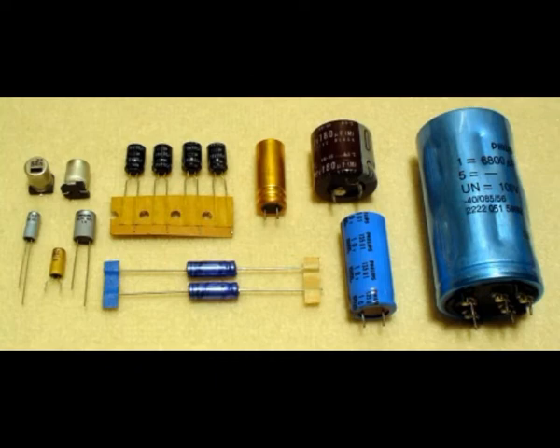This very slow drying out of the electrolyte depends on the series construction, ambient temperature, voltage and ripple current load. Lowering the electrolyte over time influences the capacitance, impedance and ESR of the capacitors. The capacitance decreases and impedance and ESR increase with decreasing amounts of electrolyte. The leakage current decreases because all weaknesses are healed after the long forming time.